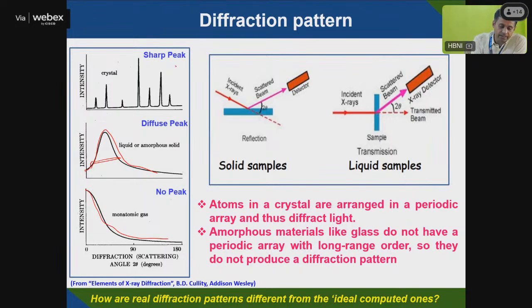In a crystal, you will get sharp peaks, because the atoms are arranged periodically and are very closely spaced to each other. There is long range ordering. But in an amorphous material, there is a random arrangement of atoms, though over a short range they may be ordered. Because of the short range ordering, you are getting a broad peak. There is no long range ordering, so you will not get the sharp peaks seen in crystalline material.